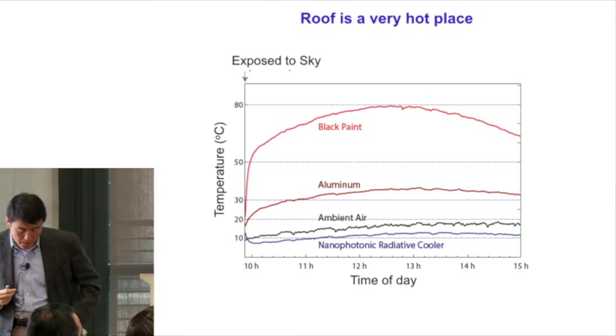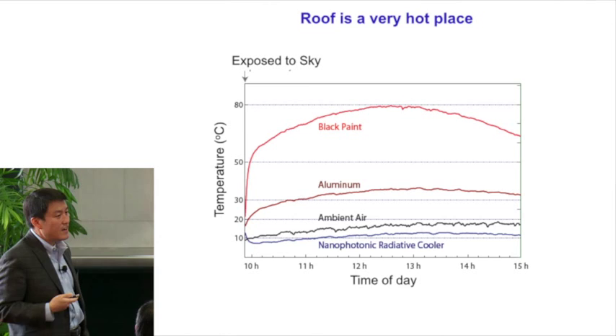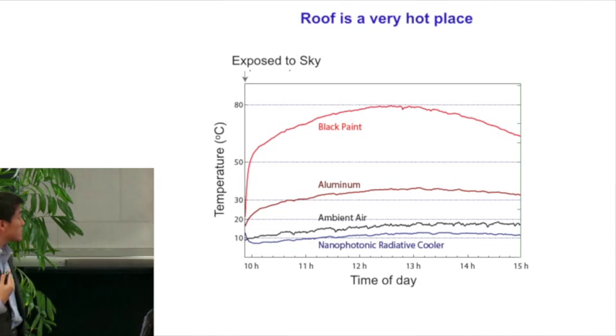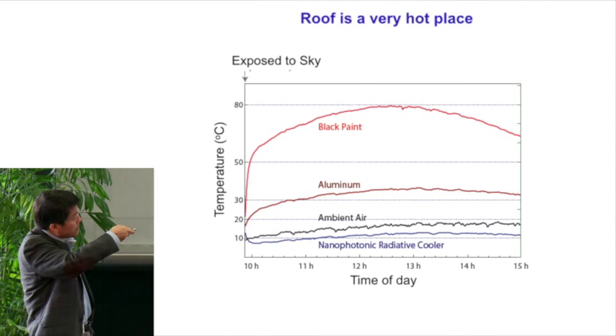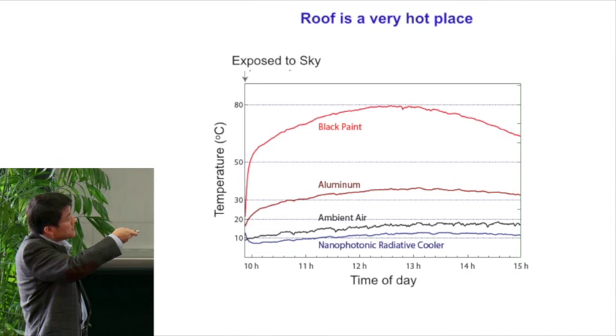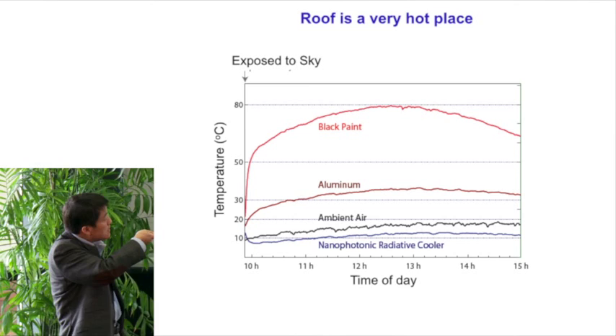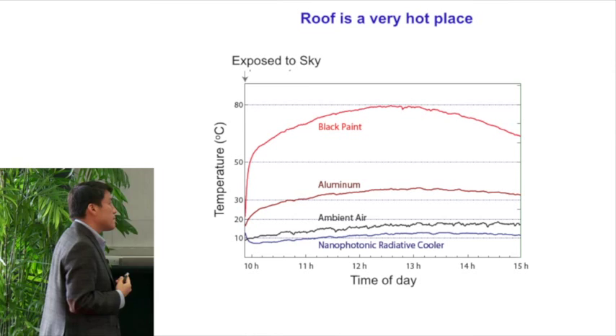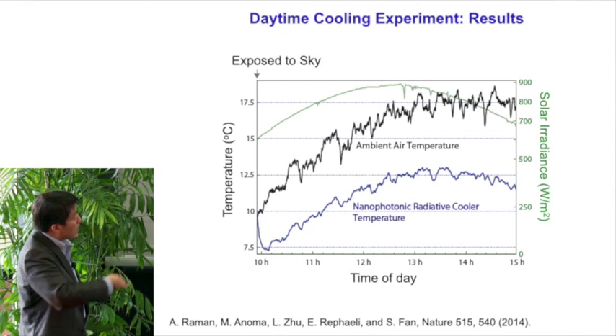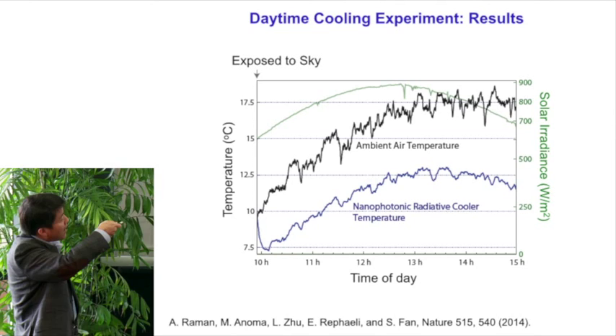So for example, if you put a black paint there, the temperature very quickly rises up to 80 degrees Celsius. Not surprising, of course, you do solar thermal with this. Somewhat more interestingly, if you put aluminum in there, even though aluminum is a very good reflector already, you will still have a very substantial heating effect, on the order of about 20 degrees Celsius above ambient. The cooler that we put in is the only structure that actually has a lower temperature under the sun. And here is a blow-up view of it. You can see that it has a temperature about 5 degrees below ambient under the peak sunlight of about 900 watts per meter squared.